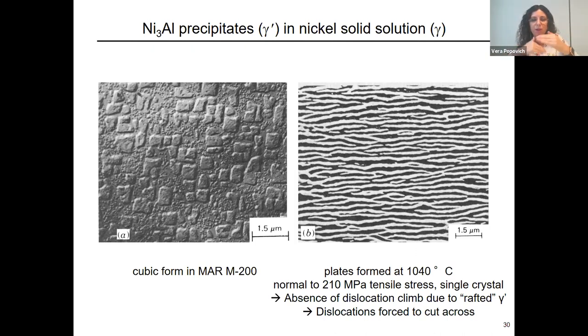And you can imagine that when the dislocations want to move, it's similar to a grain boundary. So it's difficult to cut through it. So they're forced to cut across or climb around these rafts. And this increases the strength of dislocations 3 to 6 times, this kind of effect, especially when increasing the temperature from 20 to 700 degrees.